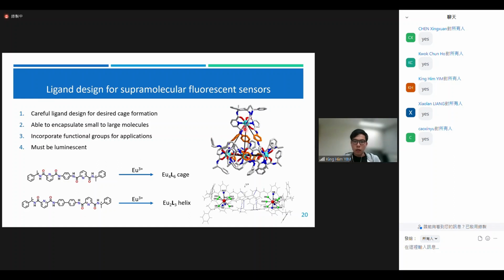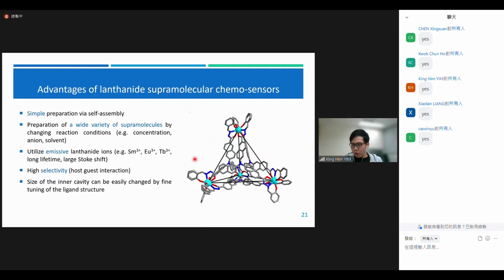So the scientist wants to make an even larger cage. So what did he do? He tried to extend the central linker into a biphenyl unit. And what he wants is a larger cage. Unfortunately, the incorporation of lanthanide ion forms a Eu2L3 helix. And that means even if you extend the linker with a very slight change, the supramolecular complex will give a very different result.